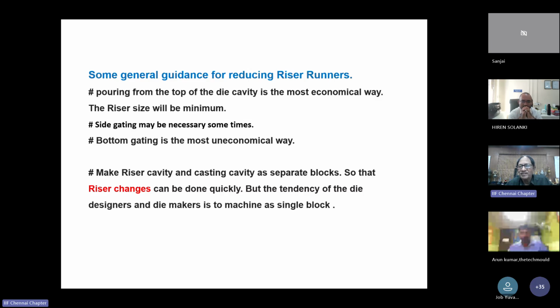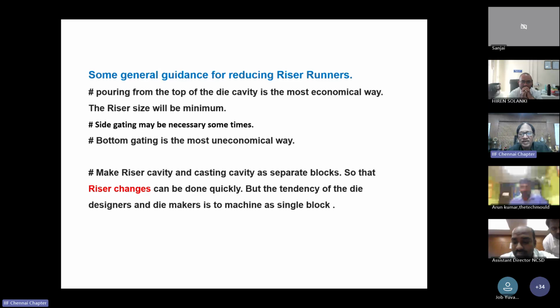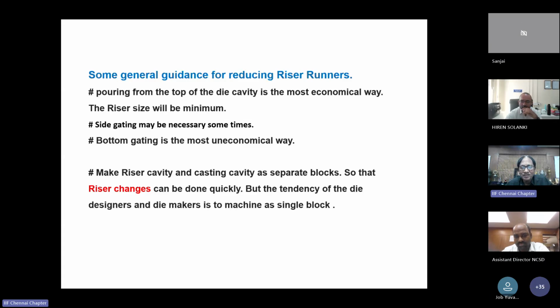Pouring from the top of the cavity is the most economical way. The riser size will be minimum. Side gating is also useful for very tall castings. Bottom gating is the most uneconomical way because of the bottom runner and the top risers. You have to pour cold metal only reaching the riser. Never go for bottom gating unless you are warranted to go for it.